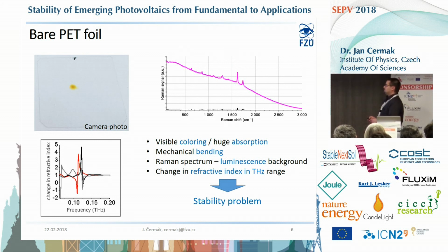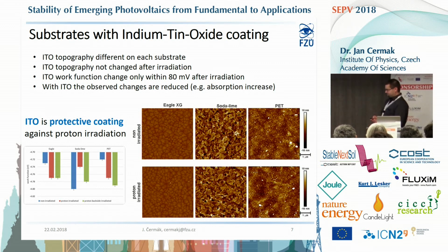There are also positive findings, and that is the indium tin oxide coating. ITO seems to be really resistant to the irradiation. Here are the AFM images before and after irradiation. For each of the materials tested, it is the same before and after. By the way, it's very nice to see that not every ITO is the same. On every sample it looks quite different in morphology, most probably due to different preparation techniques and maybe post-processing. We also tested the work function as measured by Kelvin probe force microscopy, and it showed that the work function of ITO is changed just minimally, and it should not influence the photovoltaic operation of the device to any extent.